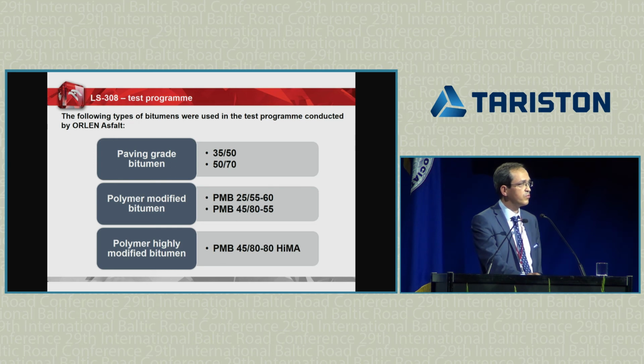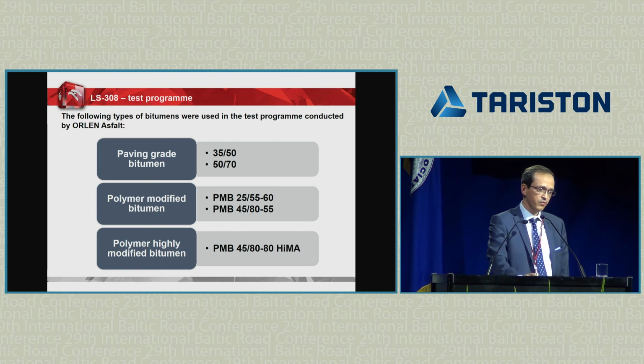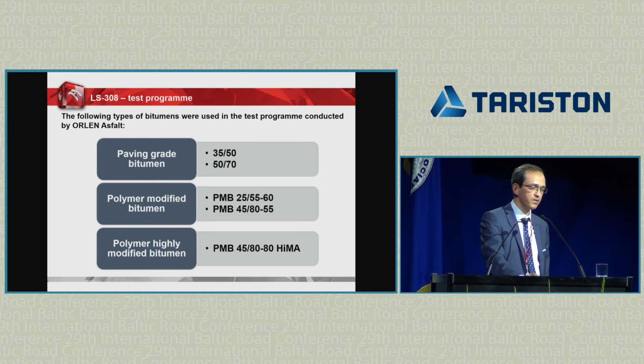At this moment, we use samples produced in the laboratory. We selected some components as raw materials, which were suspected to have a negative impact on physical hardening of the bitumens. So, as I said, we did this test for the first time ever in our laboratory. So we expected that by selecting such raw materials, we would see real effects.